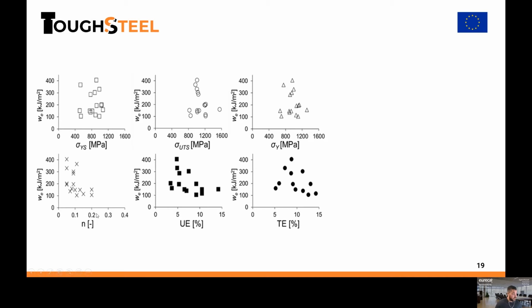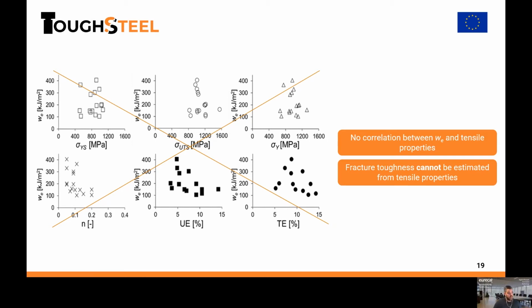Rather, on the contrary, we can see that materials, steels in this case, with higher elongation values often tend to show lower cracking resistance. This is especially critical in advanced high strength steels, because in these complex multi-phase microstructures, the deformation mechanisms that contribute to improving global ductility, measured by elongation or tensile properties, often have a detrimental effect on fracture toughness. So again, it is important to keep in mind that fracture toughness cannot be estimated from tensile properties. This is also an important message when designing new materials or new microstructures, because new materials design is mostly focused on the optimization of these global, tensile properties. But we have also seen that it's important to take into account the fracture toughness, the crack propagation resistance.